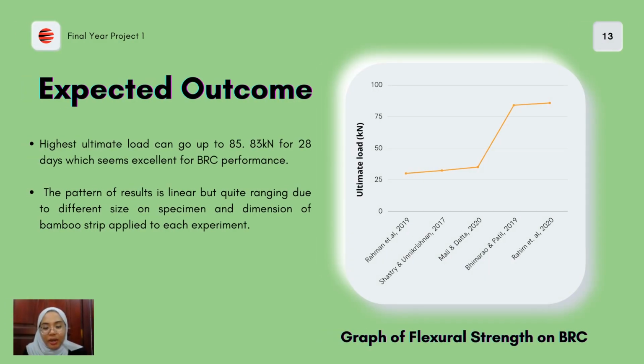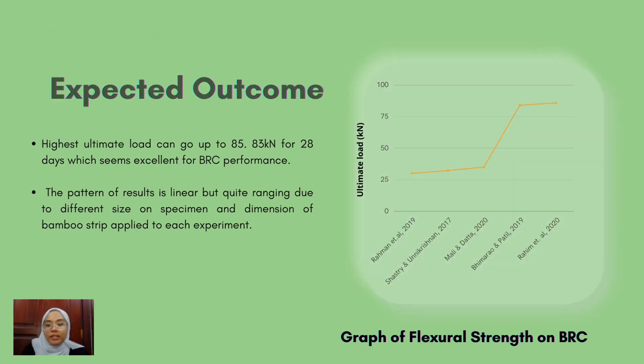For the expected outcome, I've come up with a graph on flexural strength of BRC. As you can see, I've differentiated between 5 different authors, with the highest ultimate load obtained by Bhimarao and Patil 2019 with a reading of 85.83 kN ultimate load. Therefore, the pattern of the result is linear but quite ranging due to different specimen sizes and dimensions of bamboo strips applied in each experiment.